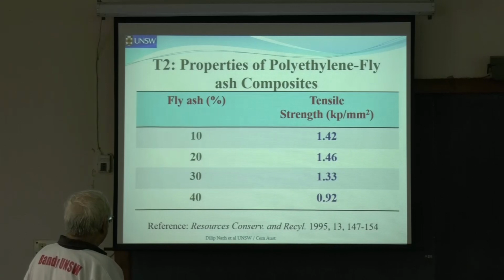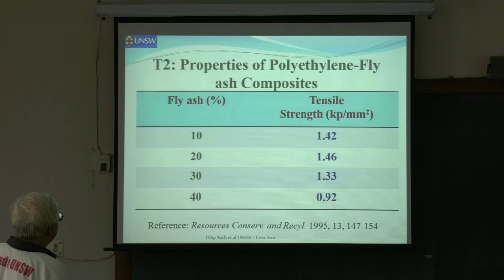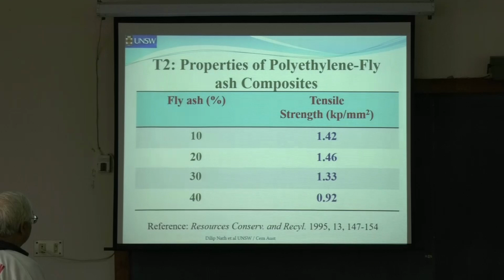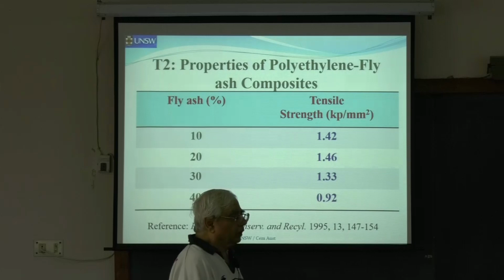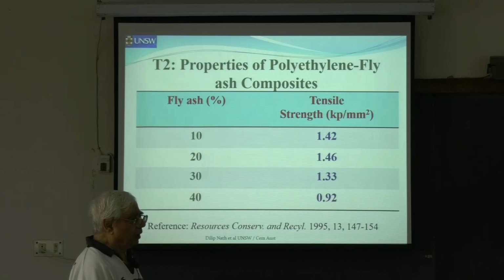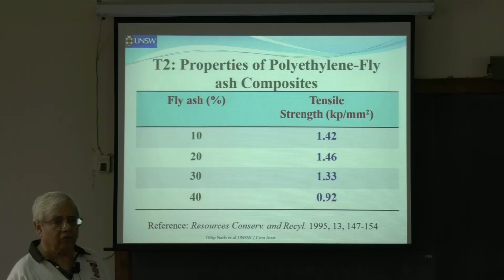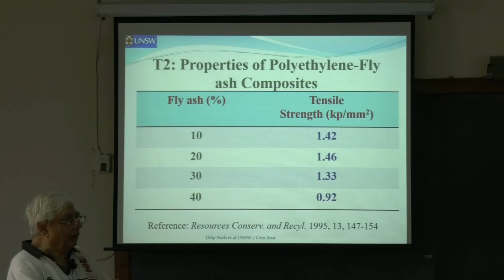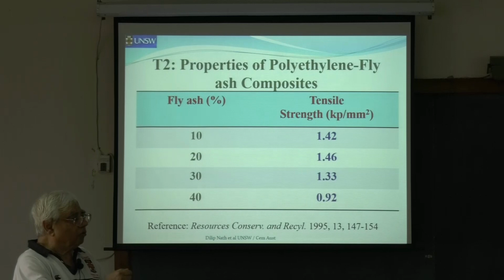Then there is another example, the properties of polyethylene fly ash composites, and again, the tensile strength tends to go down. Sometimes people get worried, but if you look from a fracture mechanics point of view, and tomorrow I'll give some lectures and tutorials in fracture mechanics, this is not too big an issue. When you are testing tensile strength, you are pulling it, and the voids are there. So the stress concentration is acting there. That's why the strength is going down, because it's failing earlier.